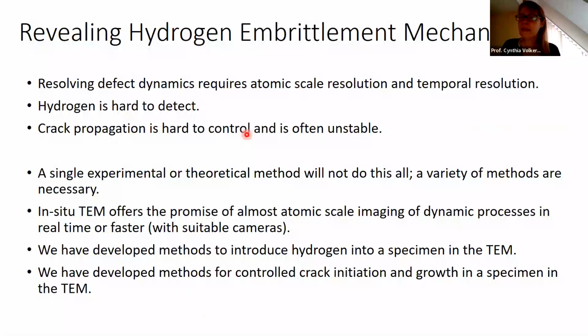So it's clear that one wants to gain control of this hydrogen embrittlement problem, but as I've just said, it involves defect dynamics that are at the atomic scale. If one wants to really understand which mechanisms are active to find ways to mitigate the problem, one needs measurements and methods that give you atomic scale resolution and sufficient temporal resolution. That's already a challenge. In addition, hydrogen is the hardest element to detect because of its lightness. And let's add to that the fact that crack propagation is very often an unstable process. So if we want to look at what's happening at a crack tip, we have to find a way to control the propagation of the cracks. These are the challenges one has if one wants to look at this problem at the atomic scale, with some temporal resolution for the dynamics.